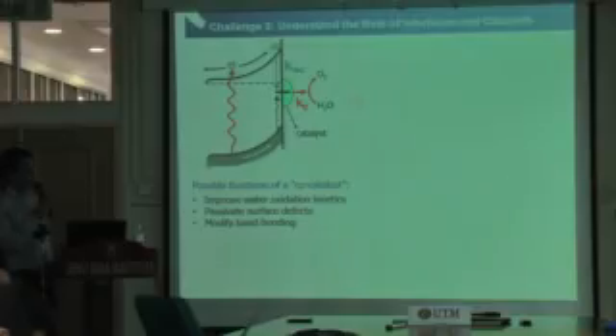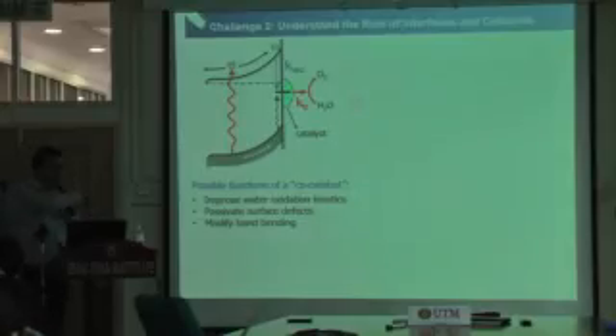So for most of our metal oxide electrodes, the catalysis, or we thought the catalysis, is actually not good, so we need to put a co-catalyst. In our case, what I showed earlier is the cobalt phosphate. So we put cobalt phosphate on top of our bismuth vanadate, and it improves the current. We thought it's a catalytic effect.